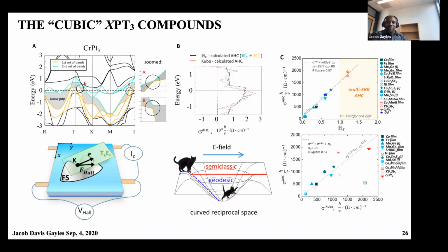So I think, me and Vivek also were PhD students together, but for the Kubo formula, a lot of problems with the Kubo formula is that it's very hard to calculate around these irregular topological points. So you need an adaptive mesh to do it, or you need many, many K points. The problem is that each point that you calculate the Berry curvature at is independent. So you need to have many points to actually reproduce things accurately. And so what we're doing here is that we're just taking the Fermi surface, whatever it looks like, we don't know what it looks like, and we throw it in and we say, how can you move on this Fermi surface to give you points that would